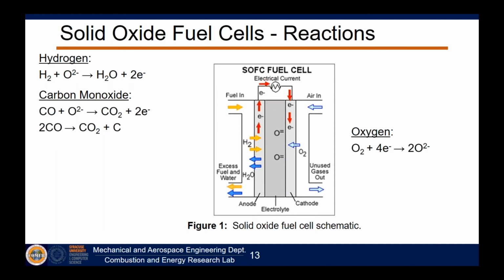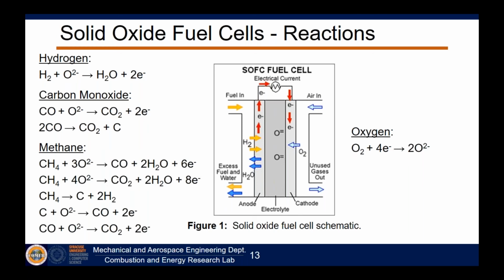We can also even think of a reaction for methane. In this case, you can think of methane reacting directly, but as you look at this picture, you can say one methane molecule and 3 oxygen ions all meeting in the same place at the same time, allowing this reaction to happen perfectly. It doesn't really happen like that from a kinetic standpoint. Generally, what we find is that methane will often actually go through a similar carbon deposition process. The carbon will then be oxidized and then further oxidized to carbon dioxide. It's a step-by-step process.